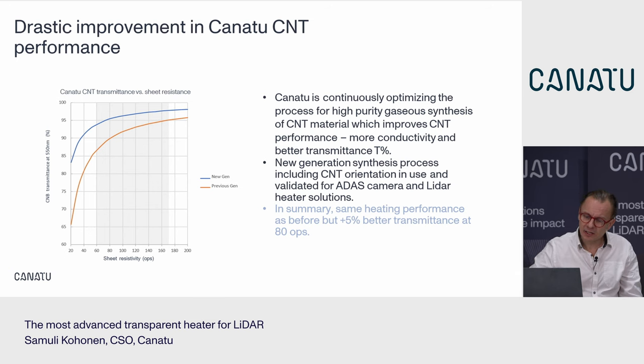The most important thing, as I said, is Canatu CNT performance improvement. So this graphic is illustrating the improvement we have been making over the last couple of years. In summary, we are able to create the same heating performance as before, but with roughly 5% better transmittance at 80 ohms per square heaters. So this is of course a really significant improvement, and our customers are extremely happy about this.